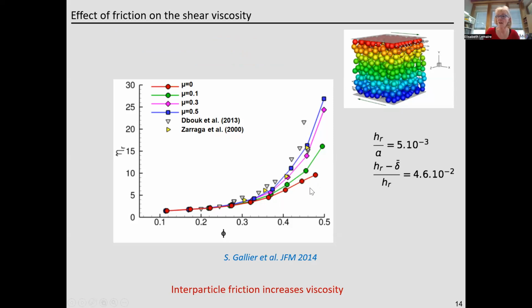Here the red curve has been obtained for frictionless particles. And when you add frictional forces between particles, then you see that the viscosity increases. It is interesting to note that when you choose a friction coefficient of 0.5, which is a very realistic value for common polymers such as polystyrene or PMMA, then the results of the numerical simulations are very close to the experimental results found in the literature. So friction increases viscosity.